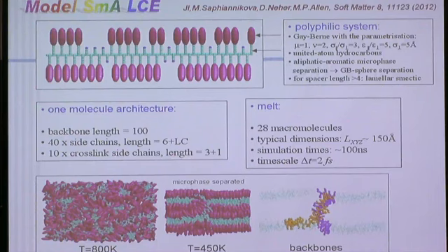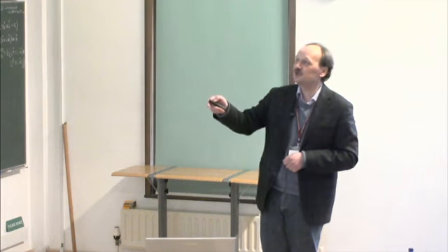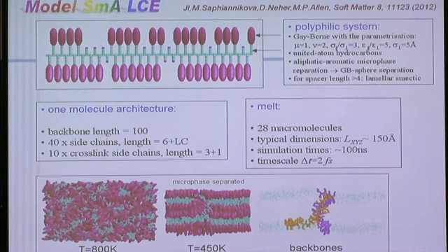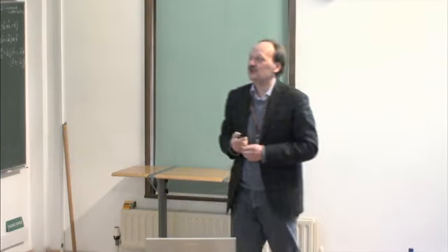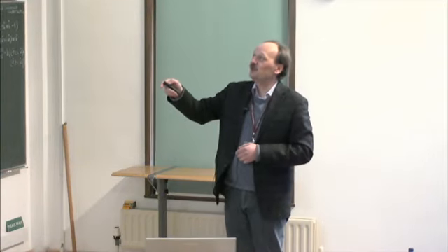So we tried to use a moderately sized system, and it is built up of the molecules that are outlined here. The backbone is made from 100 molecules, and we have 50 side chains. 40 of them are terminated by mesogenic groups in the form of Gay-Berne particles that were also discussed in several talks already. We used a united atom approach for the polymer system. Again, the previous talk addressed this type of modeling.